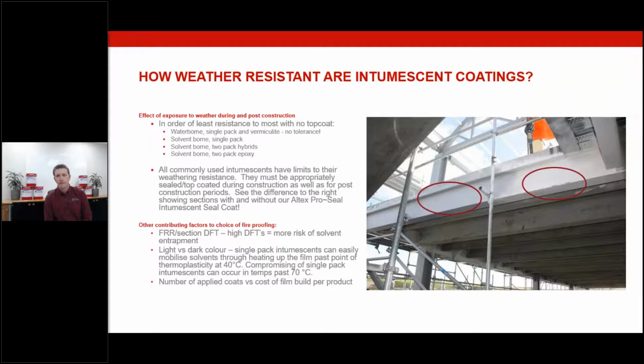For whatever particular reason, the right-hand side where you see the white has not been top coated or sealed off with the Pro Seal. This was a project in Ellerslie, I believe, by memory. Then that got cured off, and for the preceding week after that, it absolutely hosed down. You'll see on the right-hand side there, circled, that there's been actual intumescent coating degraded and knocked off the flanges. On closer inspection as well, the drip line underneath the flange was also affected. That was effectively a repair right there.